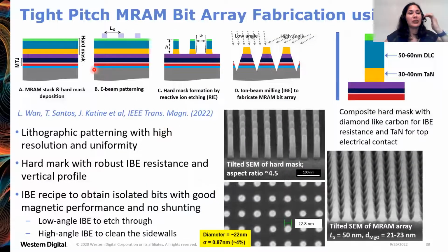So this is the experiment that we carried out in our research lab, starting with blanket magnetic tunnel junction film and the hard mask on top, the hard mask for protecting the magnetic tunnel junction during the milling process. The hard mask was defined by an E-beam lithography step, and then these hard mask pillars were made by reactive ion etching. The hard mask is made up of tantalum nitride, diamond-like carbon, and chrome. And I'm showing here this tilted SEM image of the hard mask pillars.